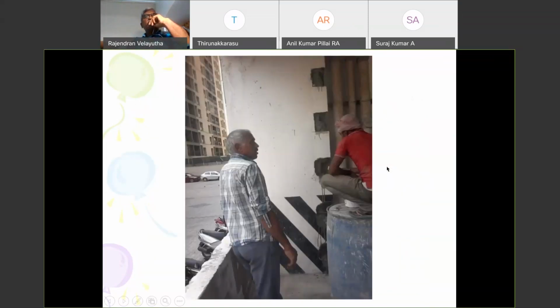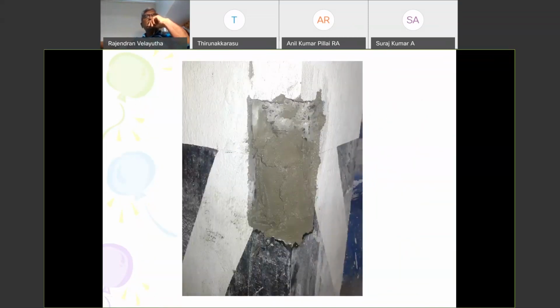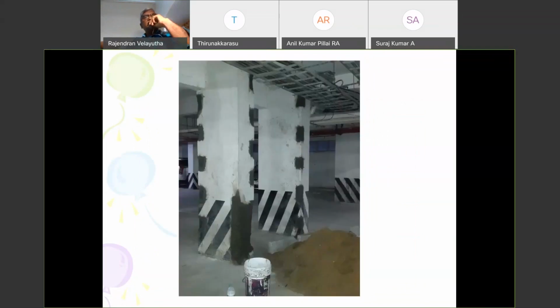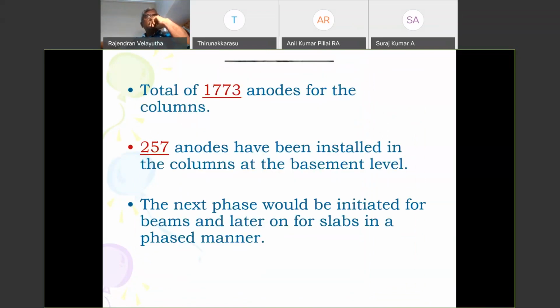So this is a system that is being used in the industry, where these anodes are placed at regular intervals and you don't have any issue. At this particular site, about 1,773 anodes have been calculated. How do we calculate? We have to calculate the spacing of these anodes. How do we do the spacing of the anode? You have to calculate the surface area of the concrete and the surface area of the steel to be protected. With this, we get a ratio called the steel density ratio. Based on the steel density ratio, we can do the spacing of these anodes.